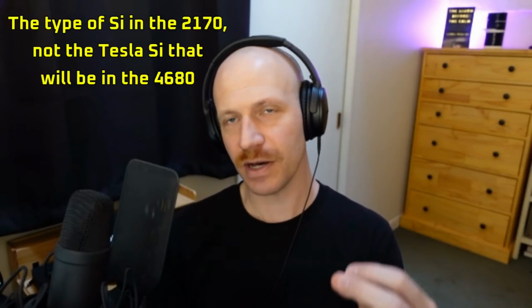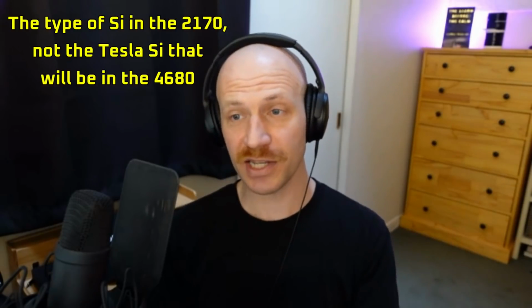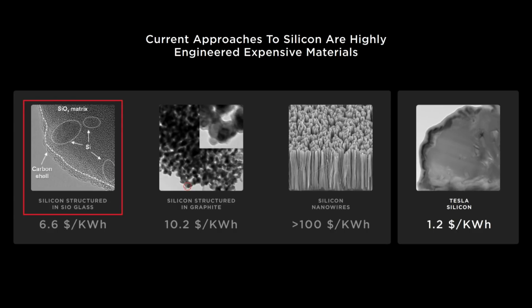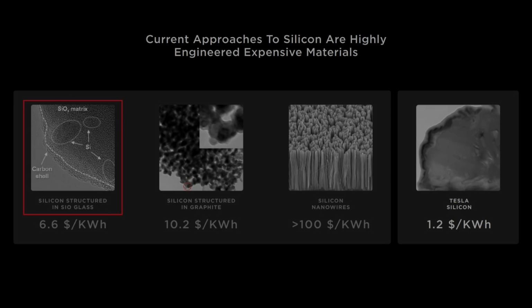All right, I'm just going to paraphrase to give people an idea of what was said there. Typically, the type of silicon that, for instance, Tesla puts in its batteries is two steps forward and one step backward. Yes, you're putting in a material that has higher energy density, but it's so poorly constructed that you lose a lot of that energy density, and you have to make up for that by putting extra lithium in at the cathode, and the cathode is the most expensive part of the battery. And with your product, there is no two steps forward and one step backward. It's two steps forward, and you get to keep those two steps.